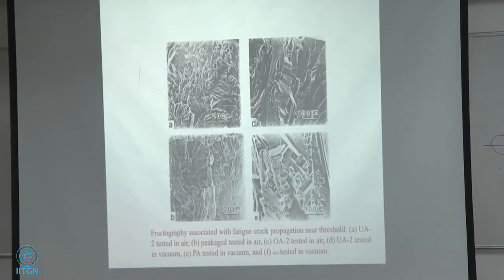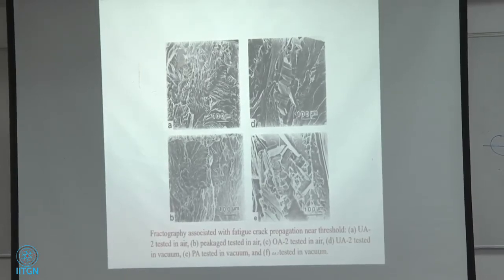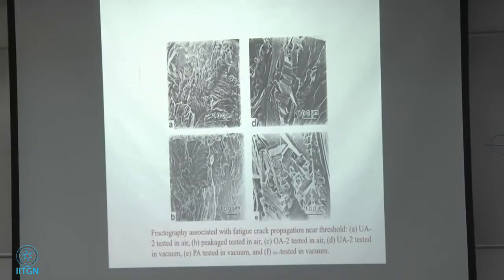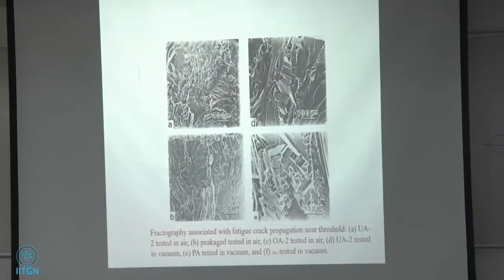Here is the one I wanted to show you. Let me put the lights off just for a second. This one. So this is a typical slip band cracking. It looks like intergranular, but it's not. It's called rough fracture surface. So these tests were done in air, and these were done in vacuum, where there is no air.